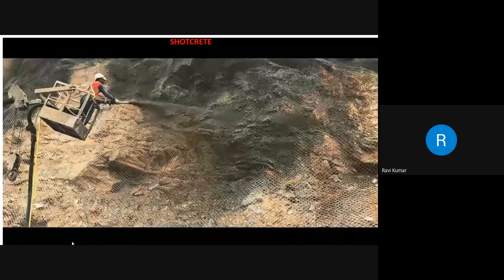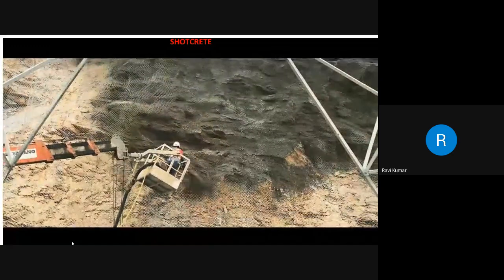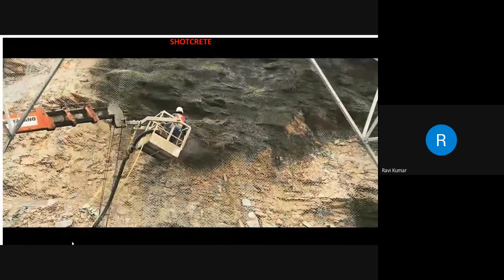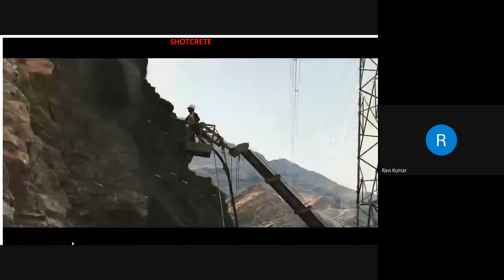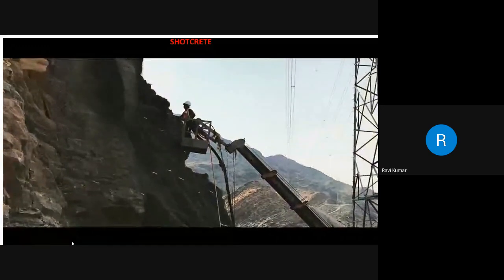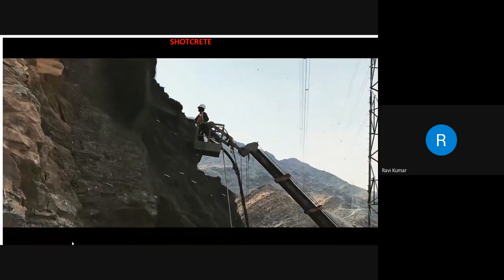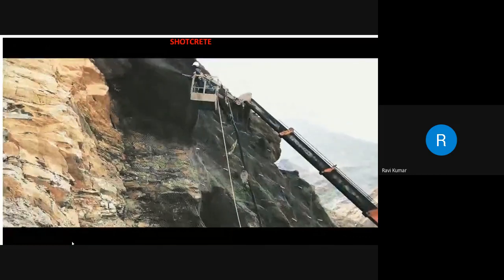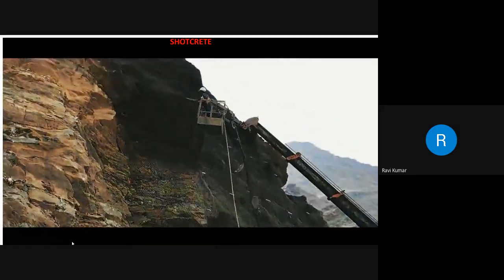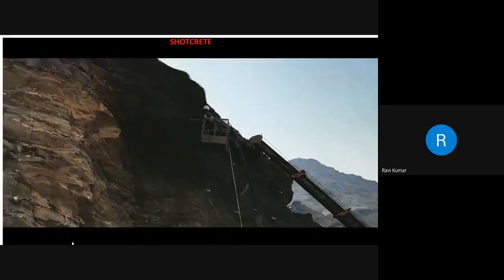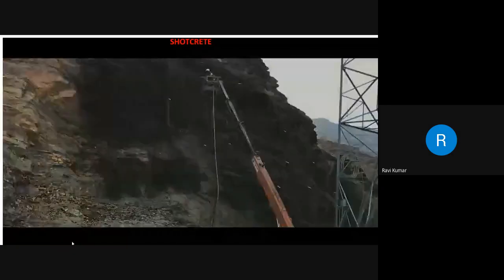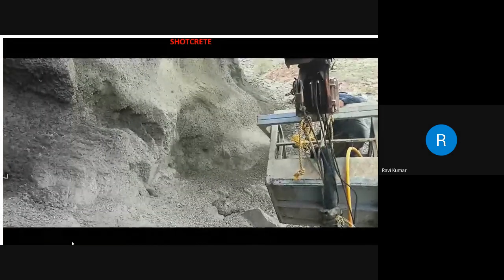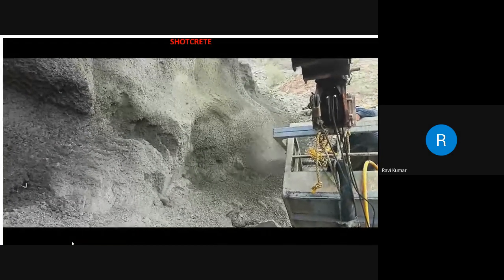Apply shotcrete evenly to targeted surfaces. Build up the desired thickness of shotcrete, approximately 10 to 15 mm. If you are going for a 40 mm thickness, voids are found and wastage will be more. Further, spray the concrete once the earlier sprayed concrete has attained strength. By using this type of methodology, you will get a well-defined, well-bonded output.